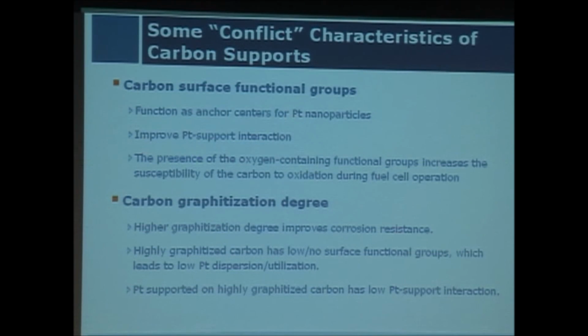Another one: okay, carbon is not good, how about graphitizing it, making it like graphite? That's great. You significantly improve the graphitization, which means corrosion resistance improves. However, when you make it more graphitized, you make the surface more inert, which means you don't have any functional groups anymore. In this case, platinum dispersion and utilization are significantly reduced. So we have to find a way to support platinum on highly graphitized carbon with a strong interaction, not like this inert one with low interaction.